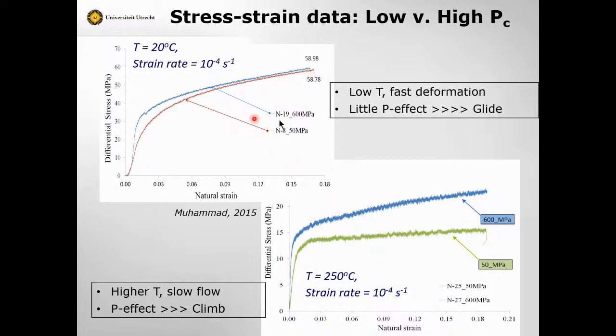And what you see here is low temperature. What we found is that at low temperature, fast deformation, there's not much effect of confining pressure. That supports microphysical models that rely on glide being the operative mechanism. The difficult stage in movement of dislocations is breaking the bonds as the dislocations move through the lattice.